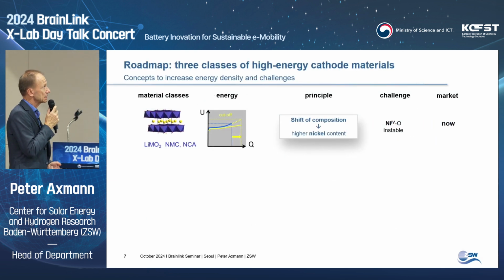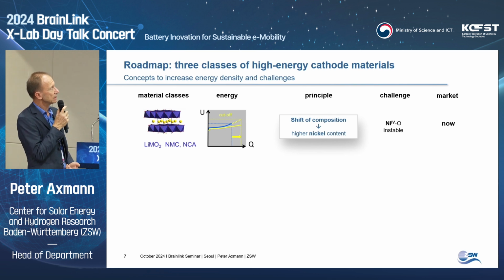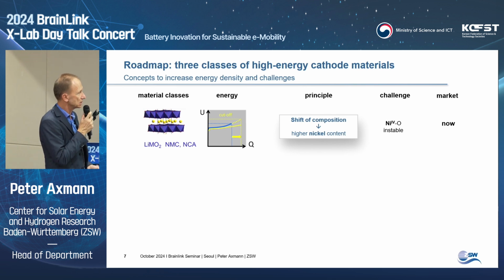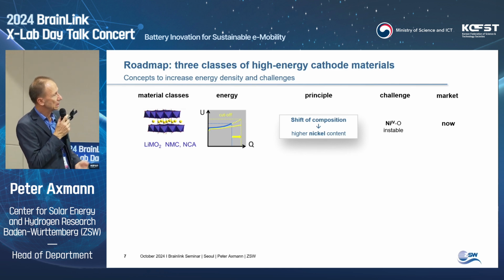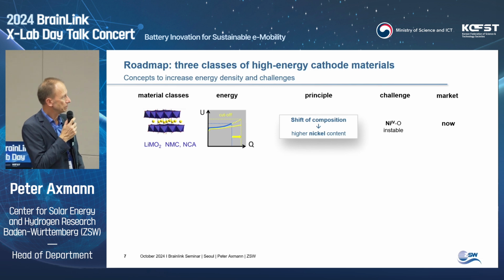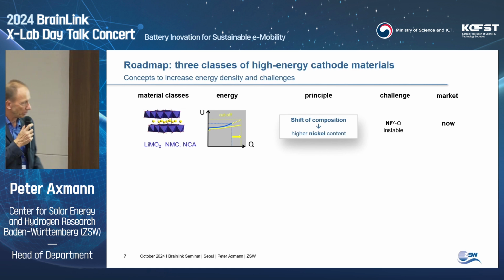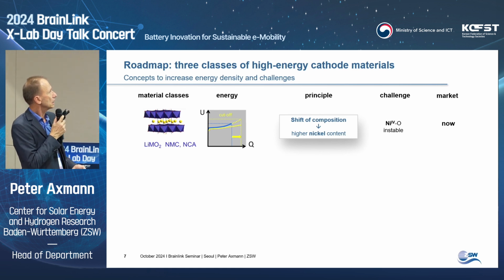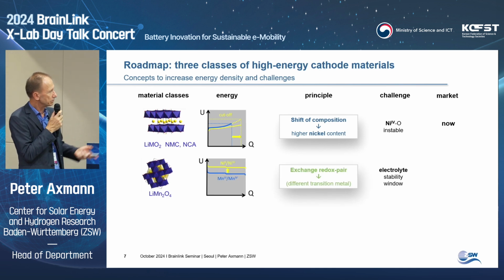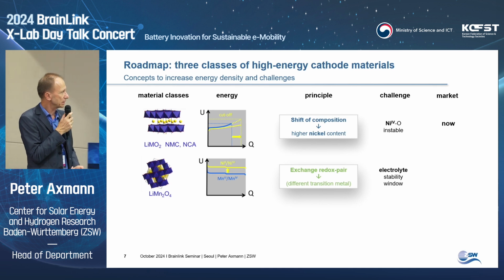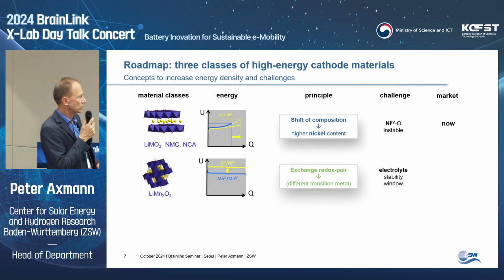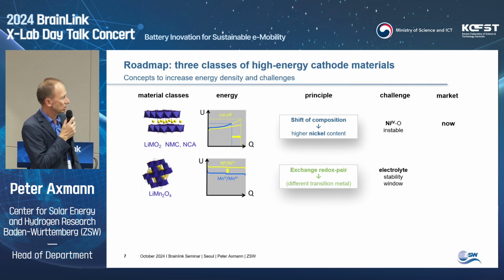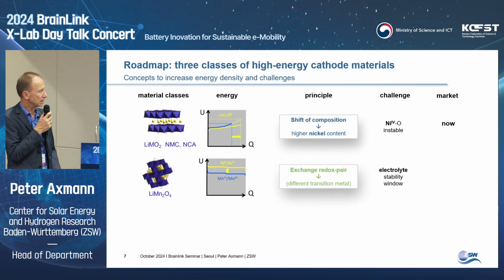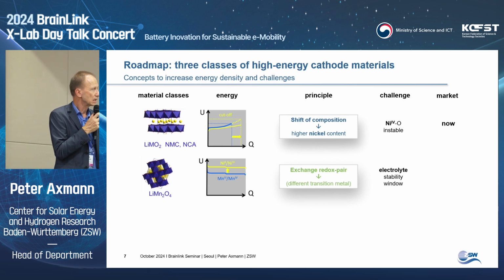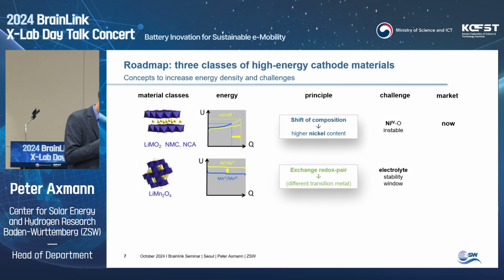And on the roadmap for these high energy cathode materials, I now exclude the olivines, are the layered cathode materials, the NMC, the nickel, cobalt, manganese materials, to increase energy. The principle is just to extend the capacity by shifting the composition to a higher nickel content. The challenge is that the nickel 4+ oxygen bond is unstable and leads to aging. Second part is the spinel, the normal nickel manganese lithium manganese spinel. Here you can exchange the redox pair and increase the working potential from 4 to 4.7 volt and increase by that directly the energy of a cell. Problem here is that the electrolyte stability window is not enough for that.